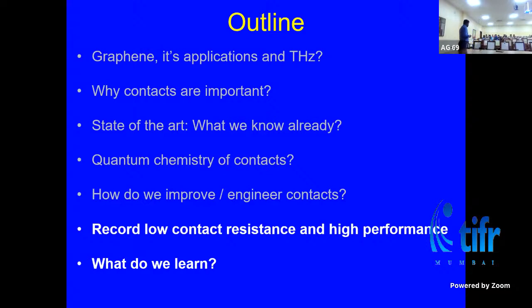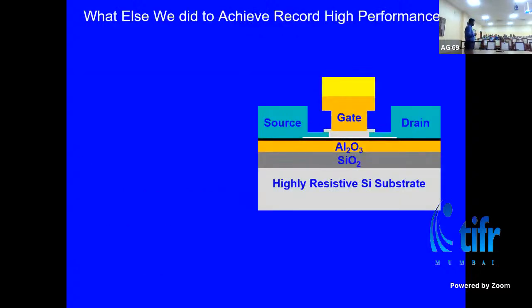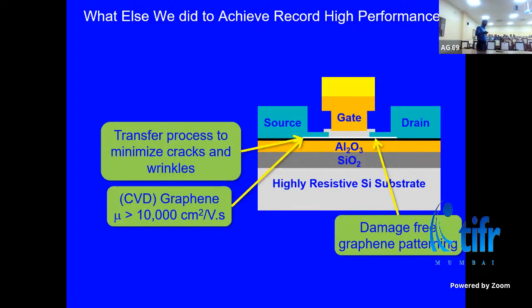So, I've shown you how to create these defects and introduce these interstitials in these systems, right? As I said, we also dealt with a lot of technological challenges. For example, in case of graphene, it is how to transfer large area graphene, and I'm talking about a few centimeters of large area graphene being transferred without introducing cracks, wrinkles. So you're growing on copper, you're transferring onto an insulating substrate, you have to dissolve copper, you have to transfer it without introducing any cracks, without introducing any contamination below the graphene layer. Even water acts as a contamination. Even oxygen acts as a contamination that gets trapped under graphene.